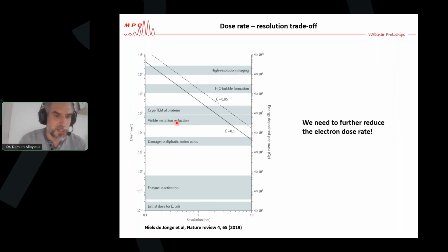You degrade proteins if you are not below the dose used for cryo-TEM of proteins, which is usually around 100 electrons per nanometer square. The reduction of metal precursors goes way below, and if you want to avoid the damage of molecules, you need to go way lower. You need to reduce further the electron dose rate. So this is clearly the main challenge of liquid phase TEM. We need to further reduce the electron dose rate.